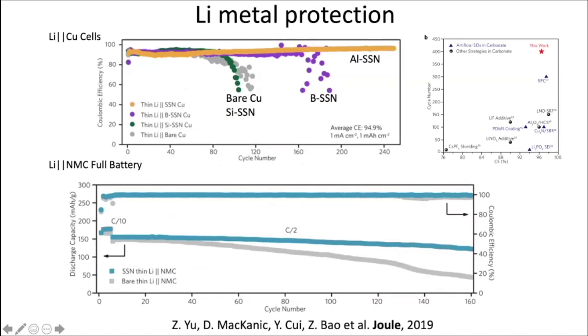And this coating, compared to the number of coatings reported in literature, is one of the best currently, if we don't use any other tricks such as a 3D host or other kind of special electrolyte. And here we're just simply using the conventional carbonate electrolyte, and we are achieving one of the best performances for full cell cycling.